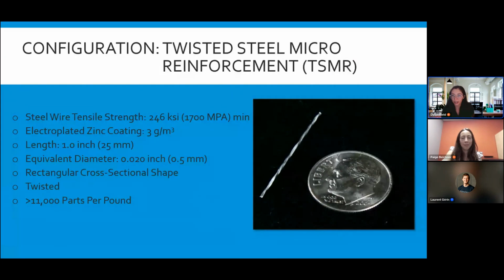So now we're into the steel options. And so the product that we offer is a twisted steel micro reinforcement, which is a little bit different than some of the other steel fibers that you may see on the market. Ours is a high strength steel, so on average it pulls around 246 KSI. It is zinc coated, so corrosion resistant. This fiber is an inch long and 0.02 inches in diameter. So the name of it gets it from its geometry. So 25 millimeters and then 0.5 millimeters in diameter. It does have a rectangular cross section, and it has at least one full 360-degree twist per fiber. All of the steel products that we do is made in Michigan, so it is an American product, which can be beneficial for certain types of work.